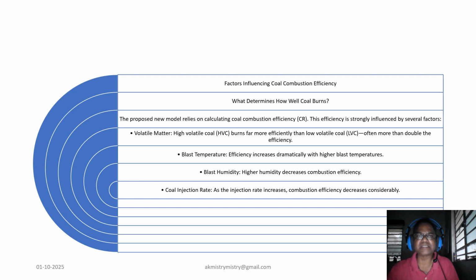Now, since coal combustion efficiency is a cornerstone of the new model, it's important to understand what influences it. The sources show that several factors have a major impact. The most significant is the VM in coal. High VM coal has a combustion efficiency more than double that of low VM coal under the same condition. Blast temperature is another critical factor. As the temperature increases, combustion efficiency rises dramatically. Conversely, an increase in blast humidity actually decreases combustion efficiency. The coal injection rate itself has a strong influence. As the injection rate goes up, combustion efficiency goes down considerably. Finally, and perhaps surprisingly, the data shows that oxygen enrichment has a very limited effect on improving coal combustion efficiency.